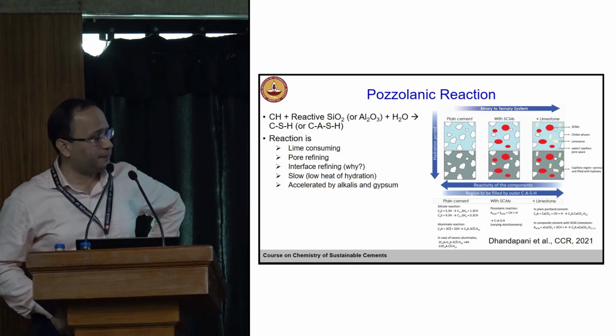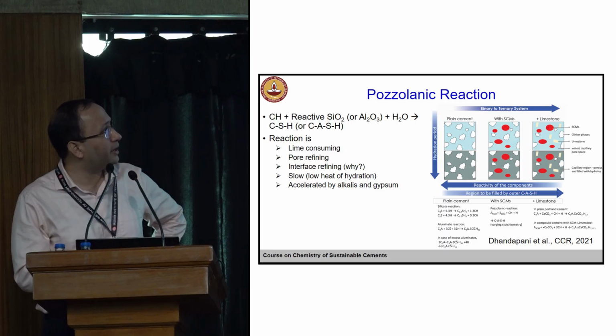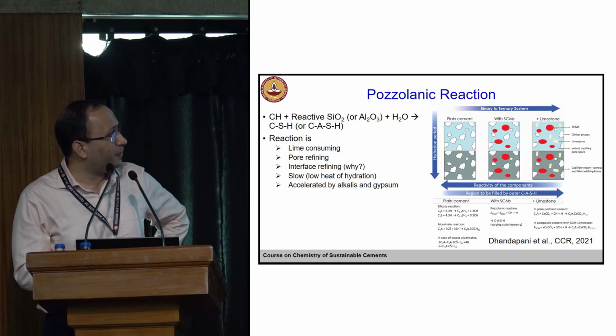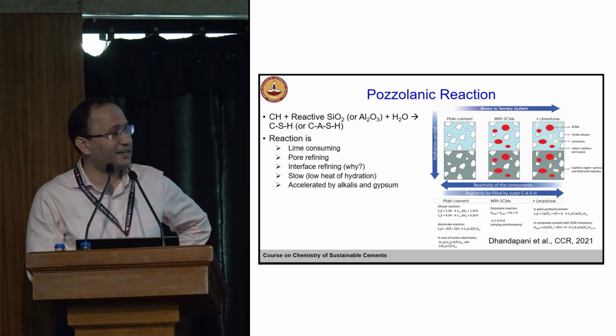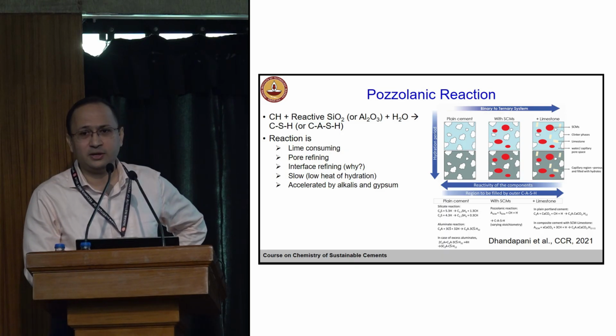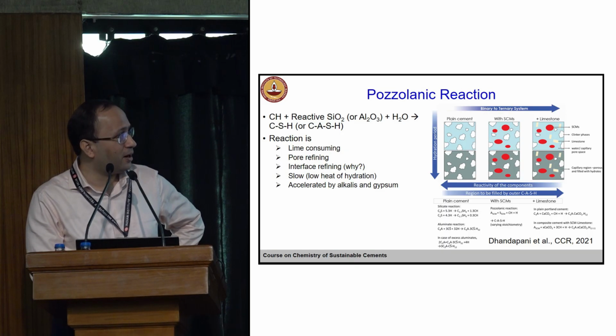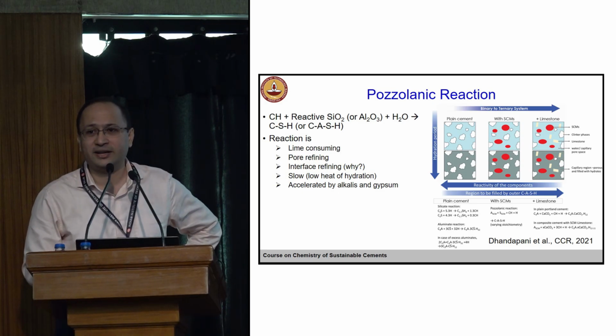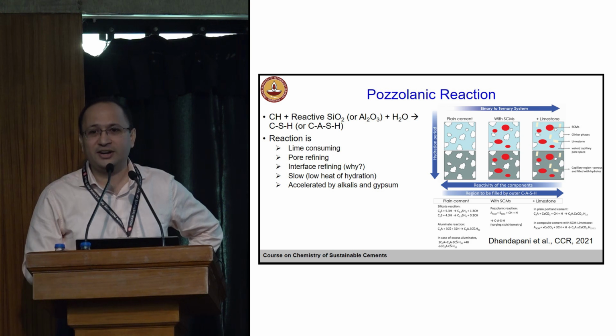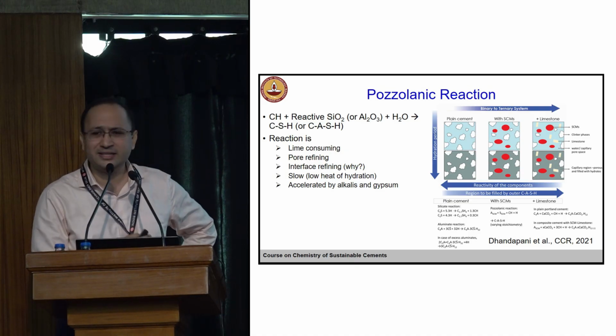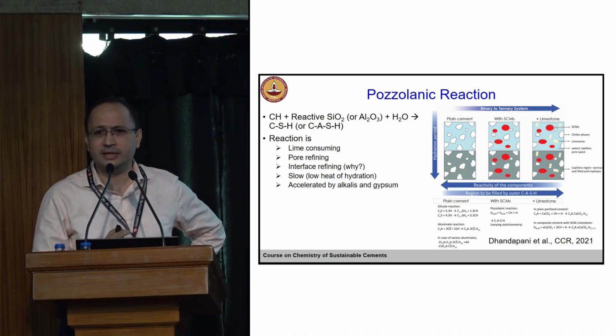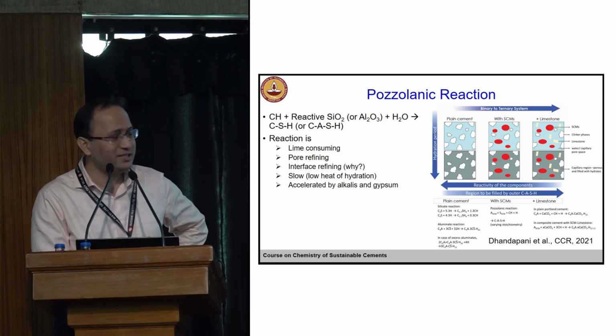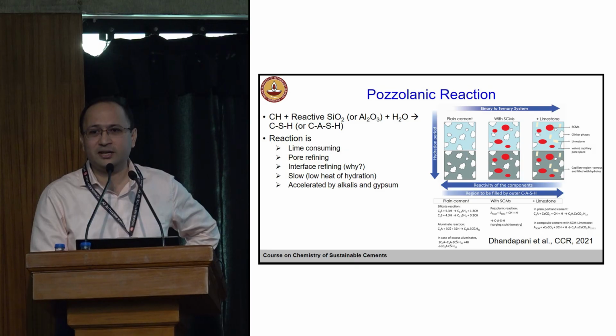Now if you look at this schematic carefully, not just SCMs, if you introduce a ternary system with limestone, which is the case in LC3, you have some additional reactions in addition to the pozzolanic reaction. You have formation of hemicarbonate and monocarbonate phases, which stabilize your ettringite. The AFt to AFm conversion doesn't happen. Anyway, we'll discuss this briefly. I hope this has been covered in LC3. I will just touch upon that. So these are some interesting synergistic effects which take place when you have, let's say, limestone in addition to SCMs.